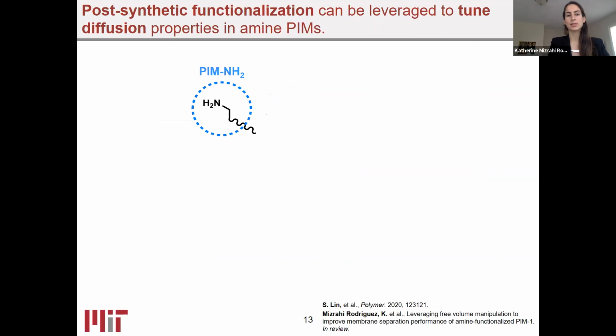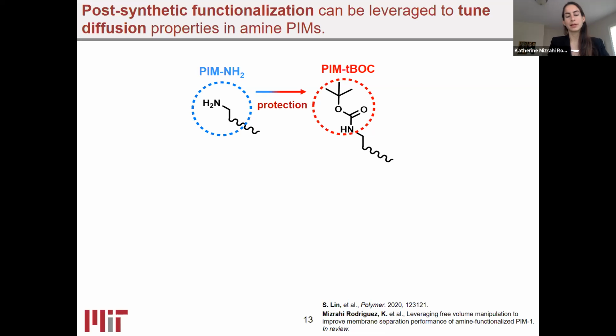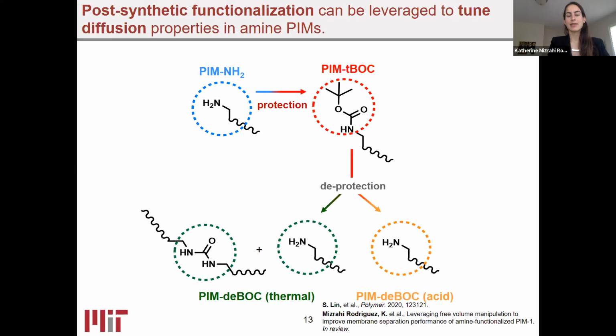So in our case, what we did is carry out a post-synthetic functionalization process where we protected the amine-functionalized PIM with a bulky TBOC group to template free volume elements. And then these were deprotected either through thermal or acid deprotection methods. In the acid deprotection case, this was performed in solution, which can swell the polymer membrane. And in the thermal deprotection case, we simply put the film in an oven at 250 degrees Celsius in order to remove the TBOC functionality.